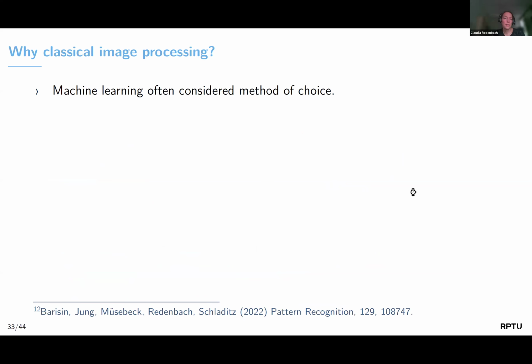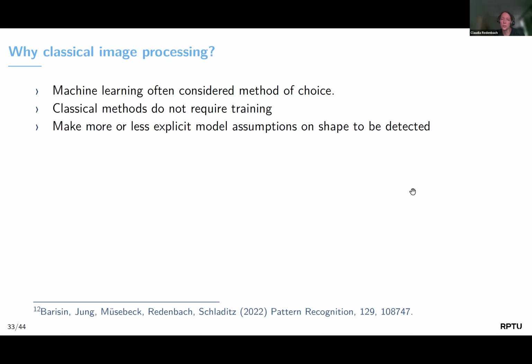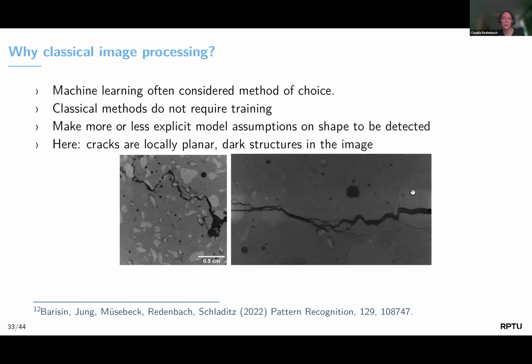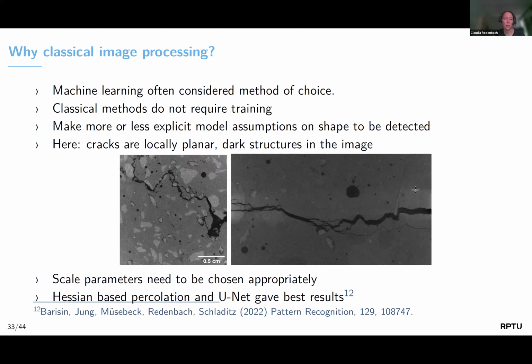Well, why would one consider classical image processing at all? Nowadays, machine learning is often considered the method of choice. Well, one point is classical methods do not require training. They are also kind of based on model assumptions on the shape to be detected. So for instance, for a crack, you could say it's a locally planar, thin, dark structure in the image. And that's basically the information that you base your segmentation algorithm on. However, what usually is required is to choose a scale parameter. So if you want to detect this very thin crack here or that very rather thick one, you would have to work with different scales to find everything. So we will come back to that.